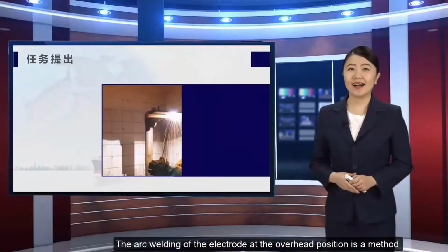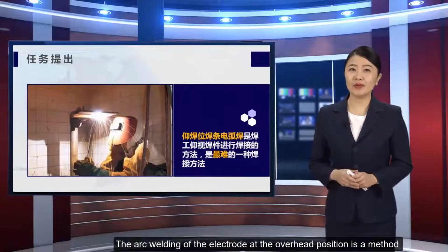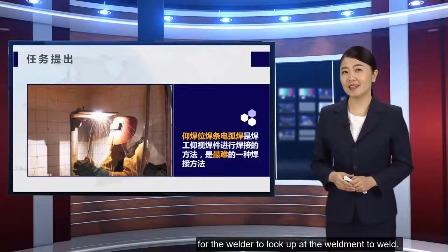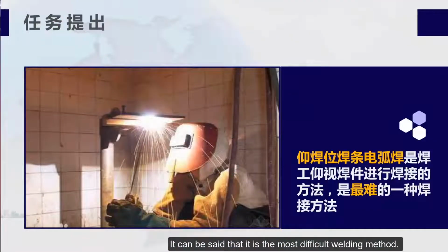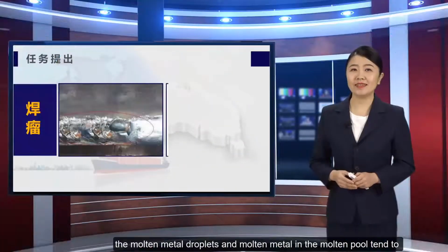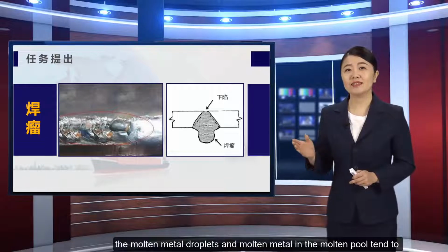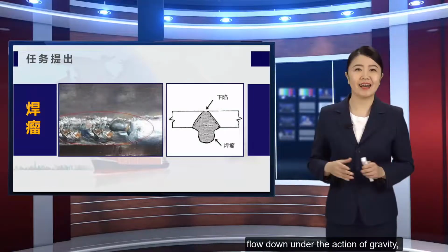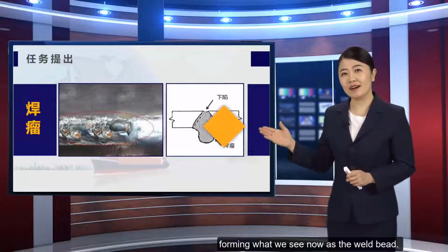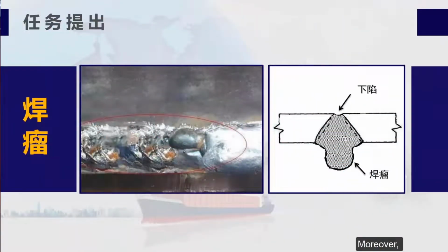The arc welding of the electrode at the overhead position is a method for the welder to look up at the weldment to weld. It can be said that it is the most difficult welding method, because in the whole welding process, the molten pool is suspended under the weldment. Since the molten pool hangs upside down under the weldment, the molten metal droplets and molten metal in the molten pool tend to flow down under the action of gravity, forming what we see now as the weld bead. Moreover, the back weld is also very prone to sag, which affects the weld formation.